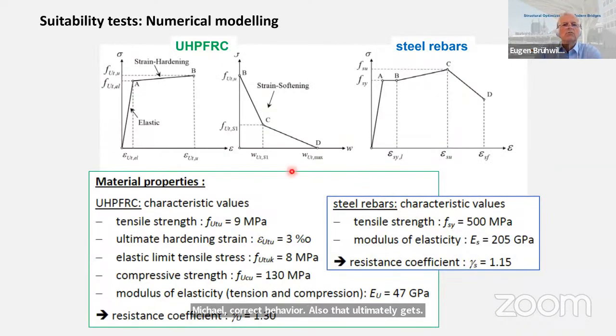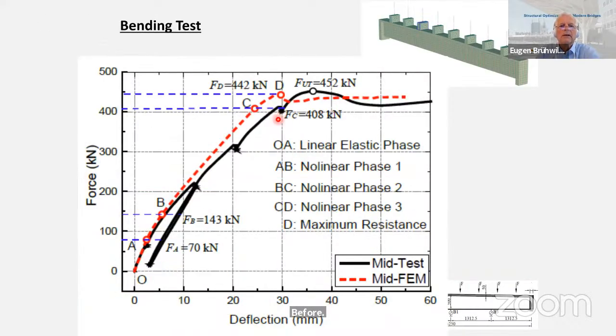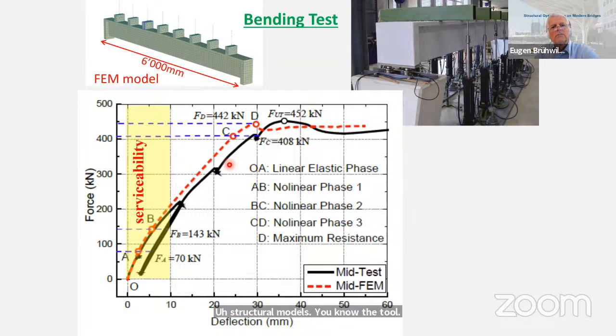Now, of course, we would like to analyze or back calculate such tests. And these are the values, the models that my younger co-workers assumed in order to calculate the tests before the tests were conducted. And here is the comparison. So they calculated the red line without knowing the black line, which is the experimental one. And we can notice that the prediction was very precise in terms of ultimate load, and the stiffness was only slightly overestimated. So we have very reliable structural models in order to analyze such beams.